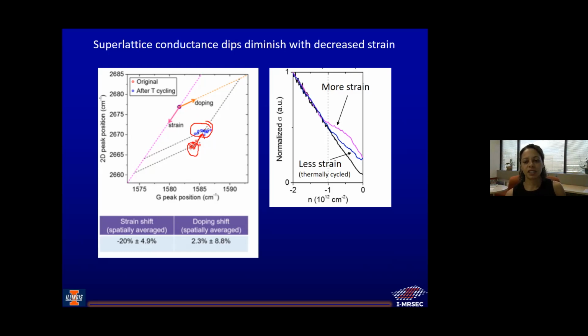And again, you can see it didn't change doping very much, but it strongly reduced strain from something like a 20% shift to a 2% shift. And then when we went back and measured our superlattice dips, indeed, you see that the less strained sample had a smaller superlattice dip. Okay, so again, this implies what we're seeing is due to changes in strain more than anything else.